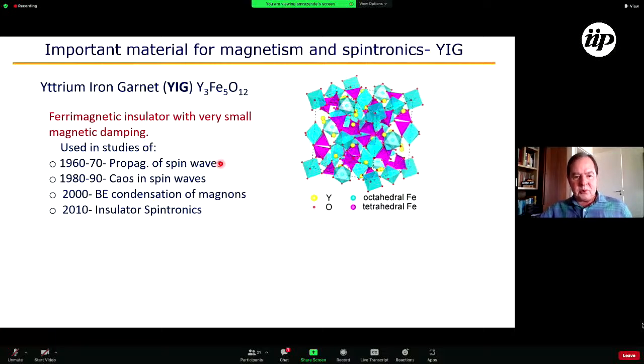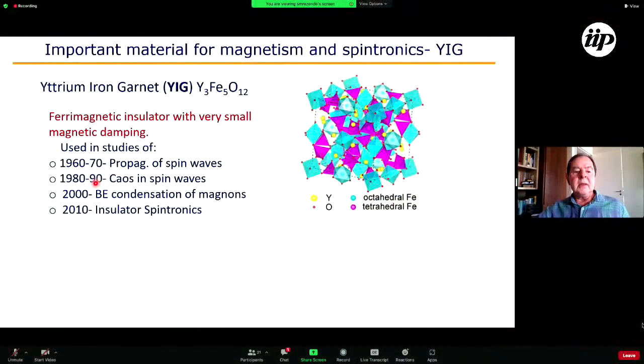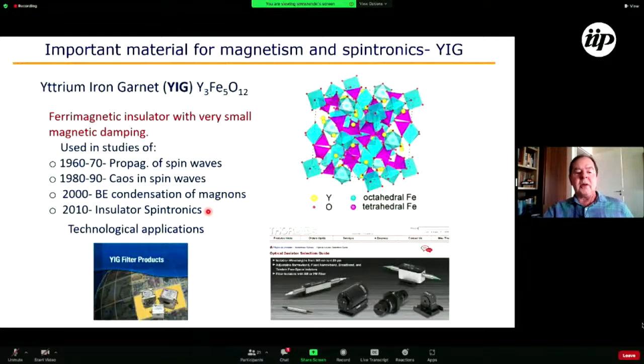YIG is important to study propagating spin waves because a propagating spin wave decays away exponentially with a decay time that is inversely proportional to the magnetic damping. So one needs a material with small damping to have a long propagation time. In the 80s, YIG was used to study chaos in spin waves. In the 2000s, it was used to study Bose-Einstein condensation of magnons. And in the last 10 years, it has been used to study what we call insulator spintronics.